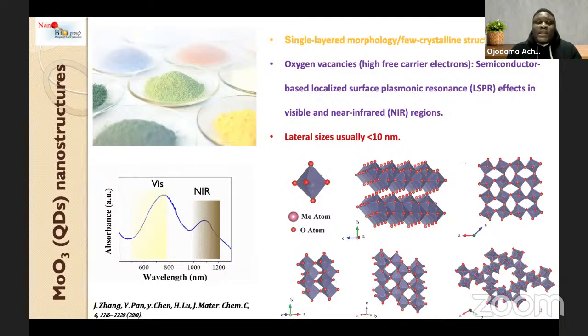But the advantage of this material is that they can have plasmonic effects, or plasmonic surface resonance, and also exhibit some good semiconducting properties, and also have some very good structures, which is a single layered few crystalline structures. Most importantly for optical-based detection or applications, they have very good optical resonances, as you can see here in the visible region and also in the NIR region. Some researchers have also, based on surface functionalization and tuning, extended the plasmonic resonance into the far IR regions. This material exhibits some very interesting crystalline structures, the alpha, beta, and the gamma crystalline structure, based on the arrangement of the crystals.